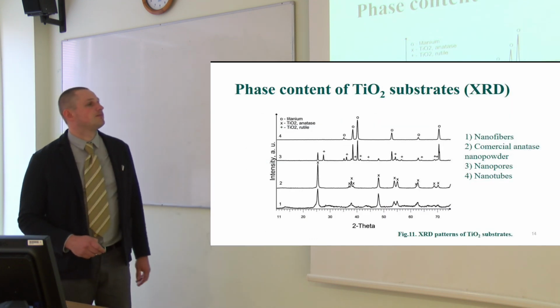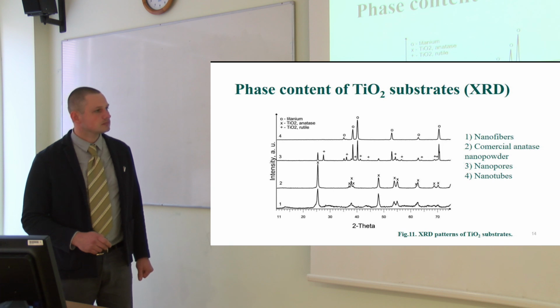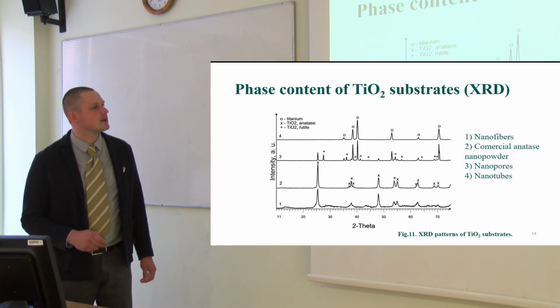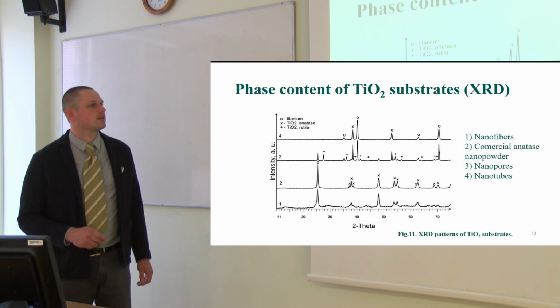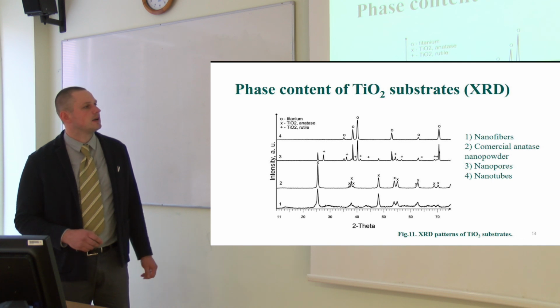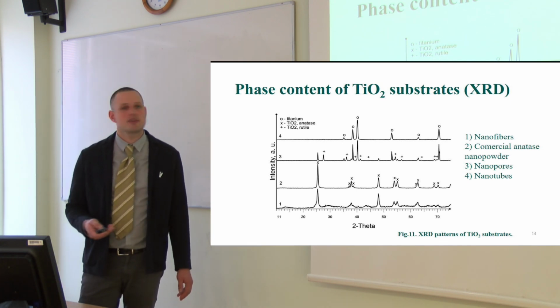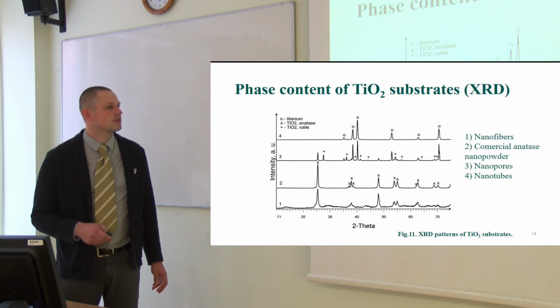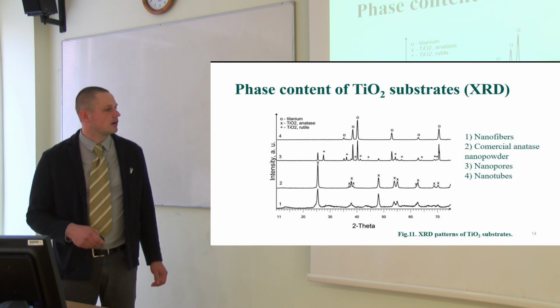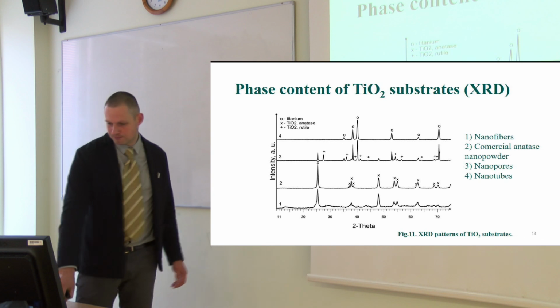So we also have tested our samples after the synthesis process to find out what chemical phases, what material phases we have in this material. So if you look at titanium dioxide nanopore coating, you can see that here is also rutile phase. It's because of the temperature during the synthesis. In other cases, the main phase is anatase. In nanofiber case, we also have some monoclinic titanium dioxide phase.